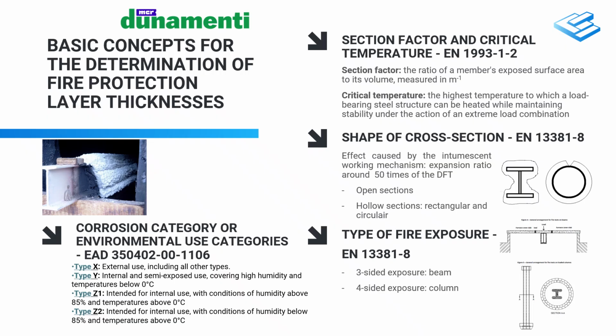The test standard distinguishes between 3-sided and 4-sided fire exposure. A beam is considered 3-sided if it's supported by a reinforced concrete slab, whereas a freestanding column, for example, is considered 4-sided. The environmental use categories based on EAD regulations also influence the fire protection solution, as the intumescent coating must also protect against these environmental factors. The type of coating system required, as primer, fire protection coating and top coat, is determined by the environmental factors. So these are the factors mentioned that determine the composition of a fire protection coating system, including its types and thicknesses.